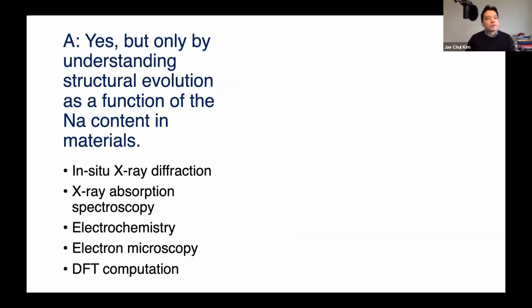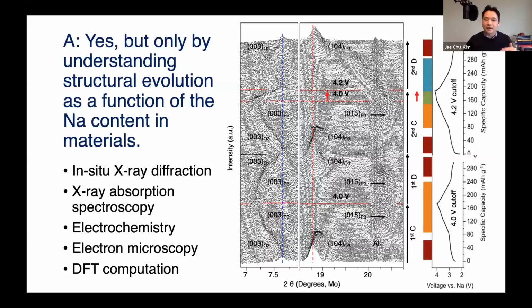The most common method to monitor the structural evolution is X-ray diffraction, but we do this in situ. So basically, it gives you a snapshot of the structure upon charge and discharge in real time. So you see there are some peaks showing the position change upon charge and discharge. By looking at these in situ X-ray diffraction patterns, we can analyze which state of charge we are at, and also do structural characterization of this material upon charge and discharge.